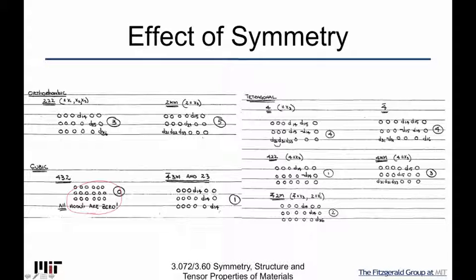Each one of these, remember how you would do it, right? You put in the symmetry group and you do that transformation of axes between the coordinate systems. If it's a twofold axis, you're rotating 180 degrees. And then you just write out the coefficients and you see which ones drop, because it can't be plus and minus, it can't be flipping sign, or changing value or anything like that. The properties have to stay exactly the same. So you have to build the tensor so that it is the same under the addition of those symmetry elements. And so you keep on doing it here.